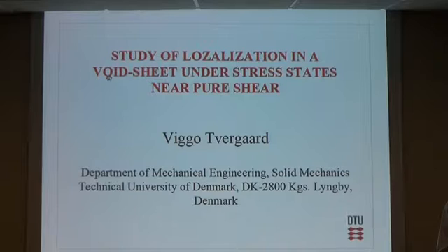I'm from Denmark, and I'm going to talk about voids in ductile solids in situations where the stress triaxiality is 0 or near 0. In previous years, I've been looking at situations where a number of voids, such as a row of voids, are subjected to near simple shear. That means they are subjected to tension and to shear, and periodicity conditions are used between cells.